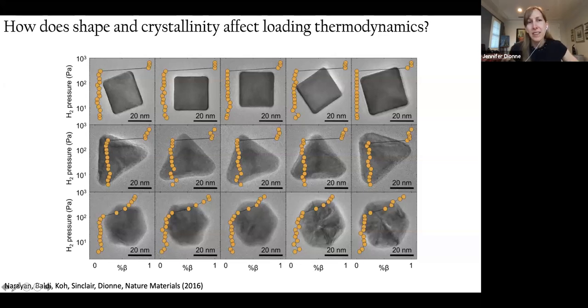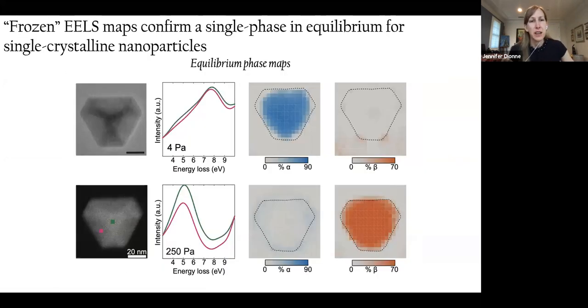Let's dive into a little bit more detail about what locally the hydrogenation state is of each nanoparticle. And if we look at the single crystalline nanoparticles like the nanocubes or the nanoprisms, and we focus our beam down and then raster scan it over the nanoparticle, we can create maps of the system in equilibrium. And I'll mention this is actually where cryo comes in, because these are longer scans. So what we have to do is flash freeze our sample to below or at 77 Kelvin, so that way the hydrogen essentially remains trapped within the nanoparticle. So we're in equilibrium, we flash freeze it, so that way we can construct EELS maps of what the phase is.